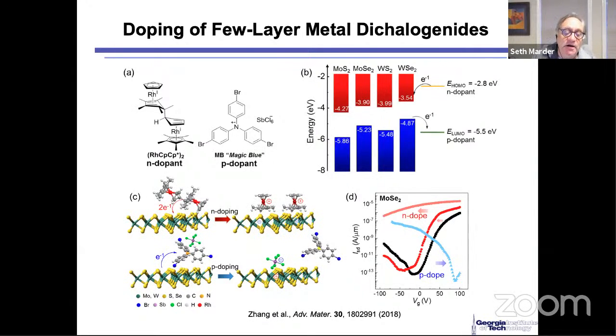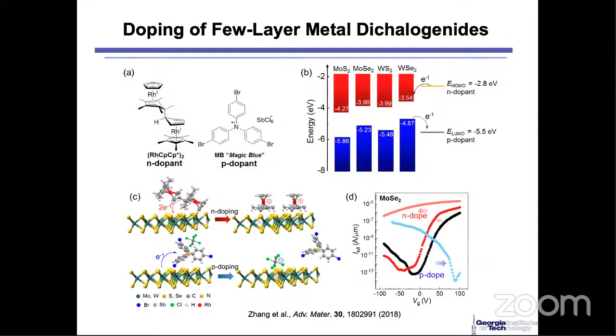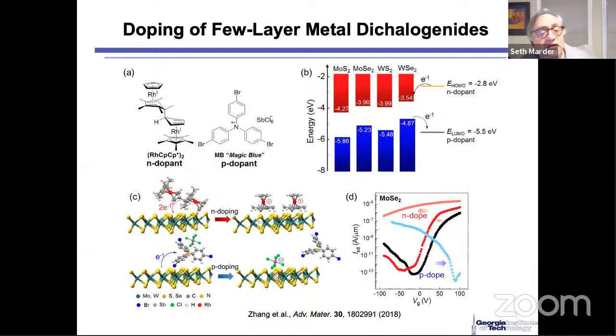Here, I just want to point out that there've been a series of papers on this, and I think this may be our second paper on this. You can take metal dichalcogenides: molybdenum disulfide, molybdenum diselenide, tungsten disulfide, tungsten diselenide. People have also done black phosphorus now, and treat it with either an N or, in one case, a P dopant. This is a commercial P dopant, but we'll focus on the N dopant. With the P dopant, it's sufficiently strong that with tungsten diselenide, you can dope it. But with the N dopant, you can start dumping electrons into these systems, dramatically changing where they turn on and off as transistors.